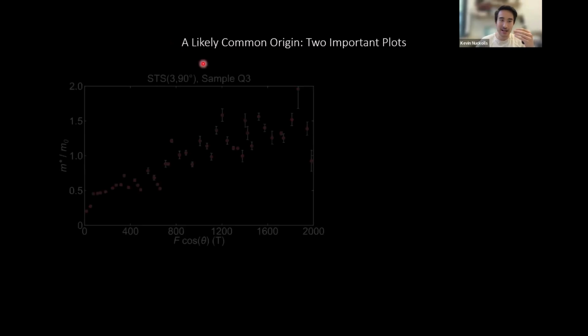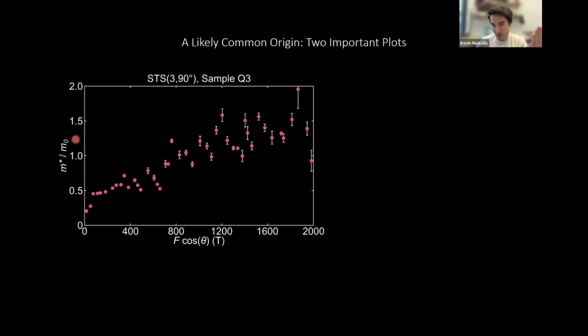So two important plots. The first is that we took temperature dependence of these quantum oscillations, and we can quantitatively extract from that the effective mass of the Fermi pockets. And so here I'm plotting the effective mass of those pockets as a function of their frequency, so effectively the scaling of the size of the Fermi pocket. And from this plot, we see nothing of note. They're effectively kind of normal Fermi pockets. They're slowly drifting from 0.5 bare effective masses up to 1.5 bare effective masses. There's not much of note in this plot.